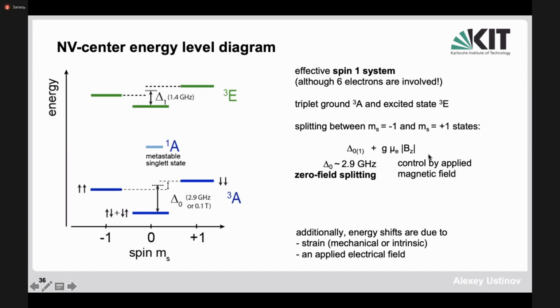And in addition, you can, of course, control the spin states by applying an external magnetic field, introducing the Zeeman splitting. So in a way, this system is very well controlled, and there are transitions in this convenient frequency range, between the ground state and those slightly split excited states. These are in the range of 2.9 gigahertz. Of course, you can also modify these states by applying mechanical strain, or an electric field and so forth, but I'm not discussing this here at this point.